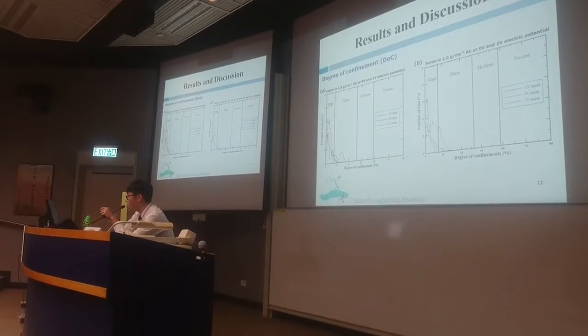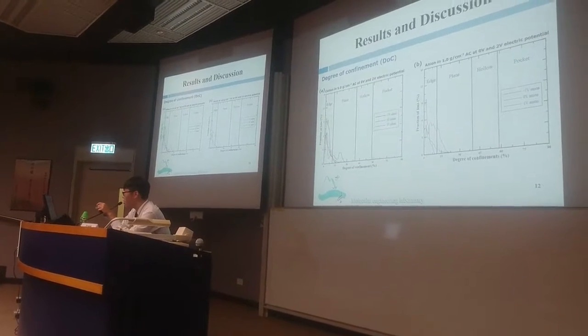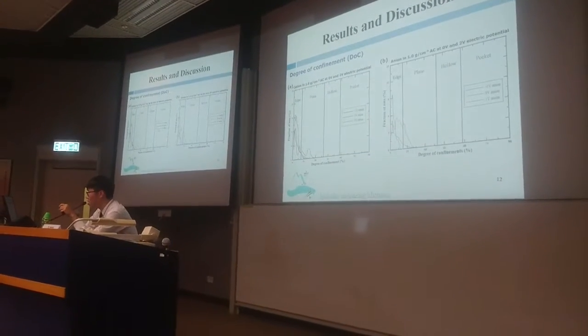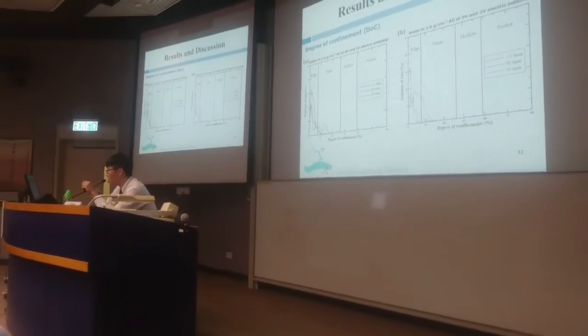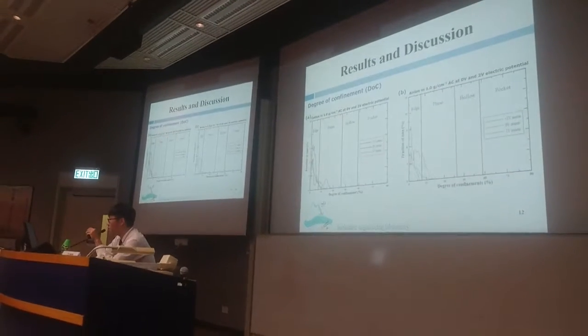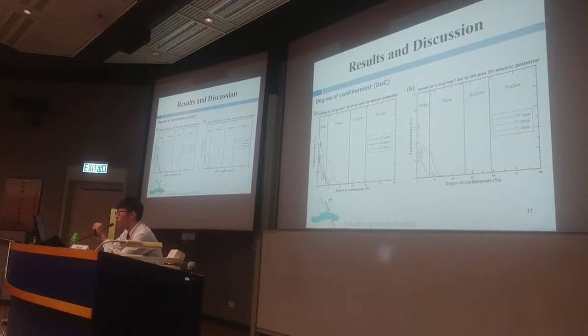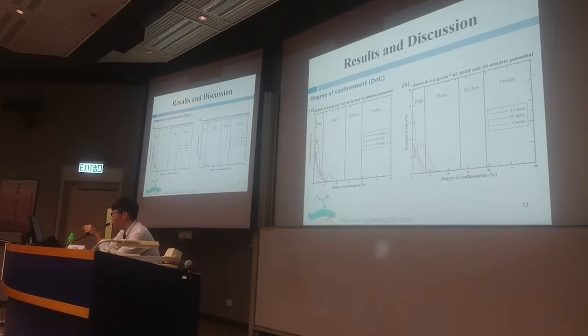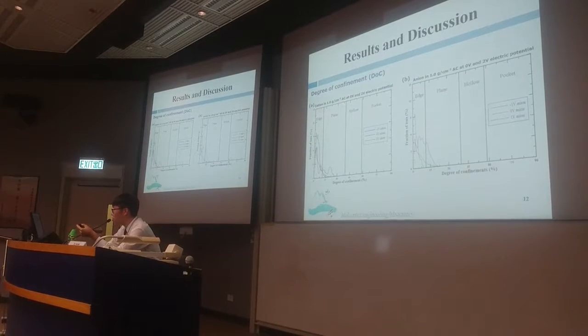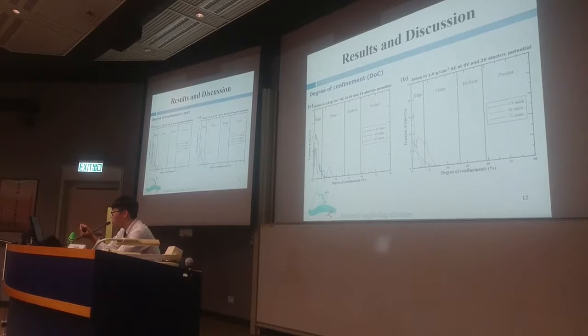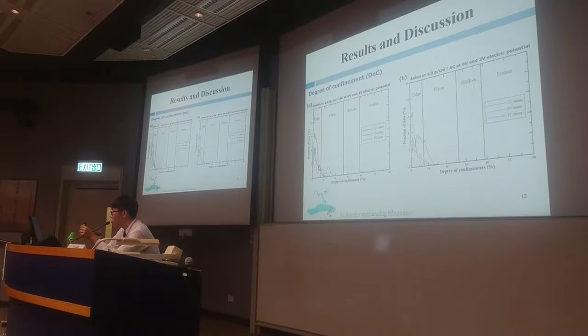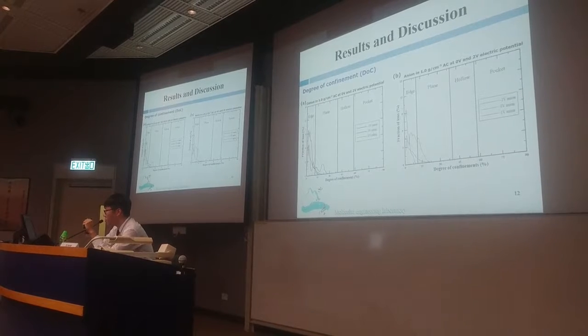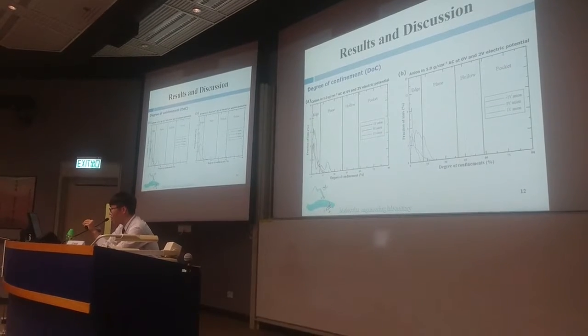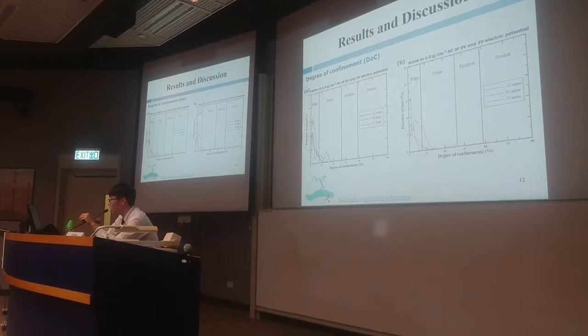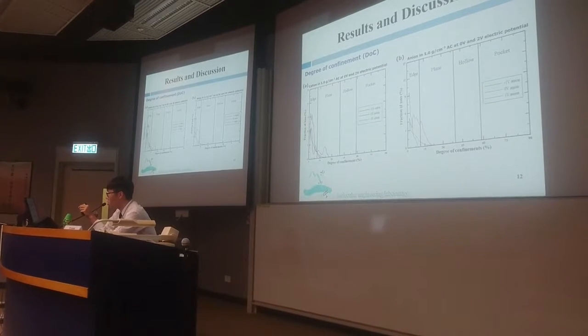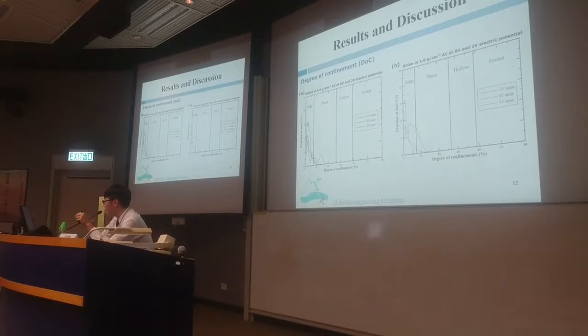These two figures show the DOC of ions in the 1.0 AC electrodes. The ion distribution has a similar pattern to the case of the density 0.8 AC. So we can find that higher density AC electrodes cannot be easily diffused by ions.